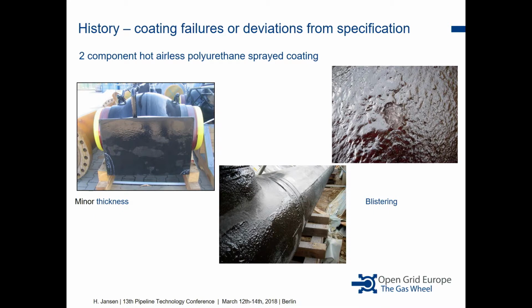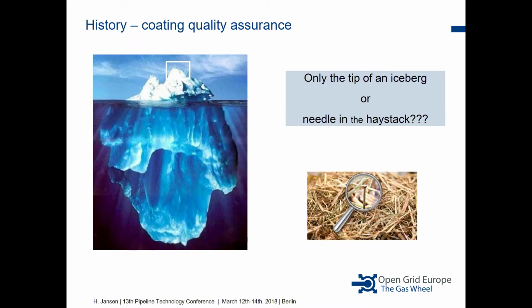You can see minor coating thicknesses on the saddle of the valve. Here you see blistering on a section where the temperature conditions had not been met, or where the humidity was too high, or where the dew point conditions have not been met according to the specification. Then you find these blisters in the polyurethane coating.